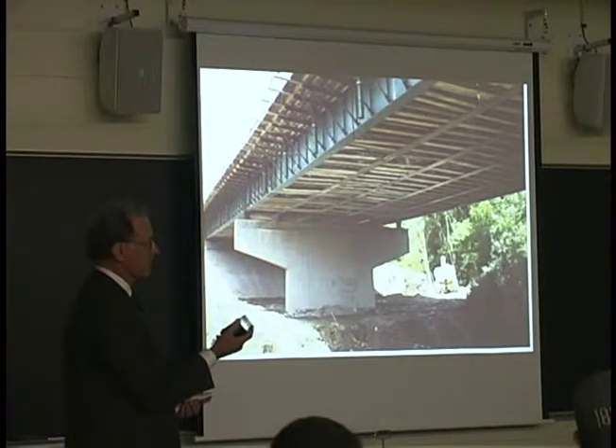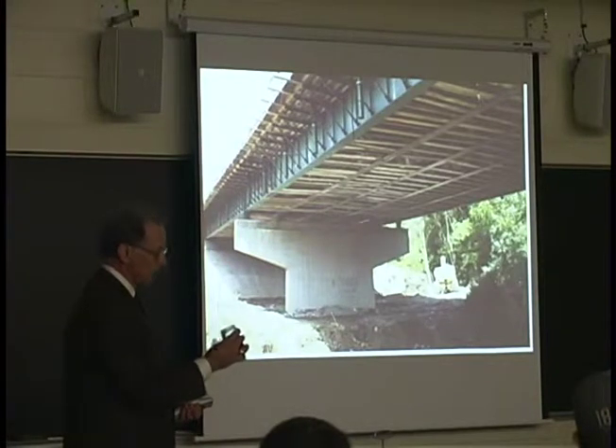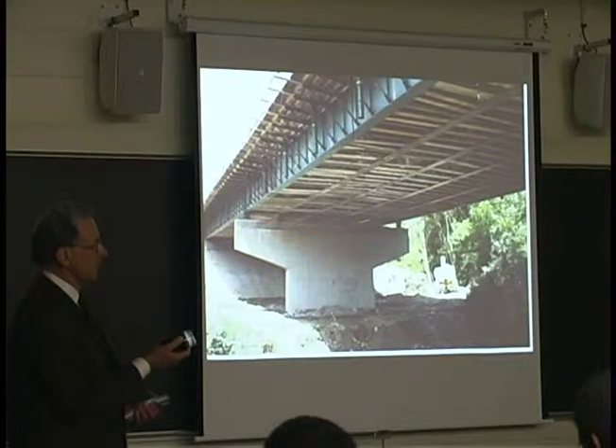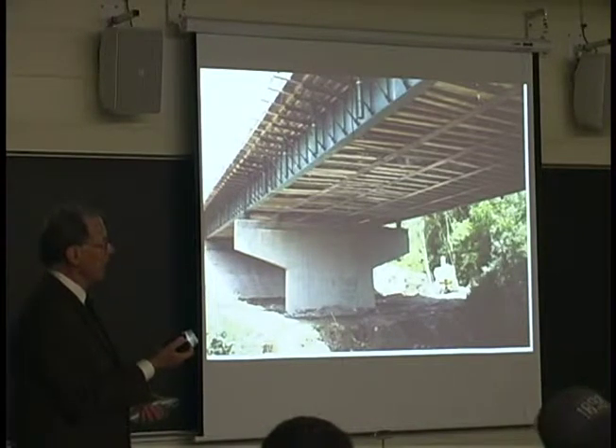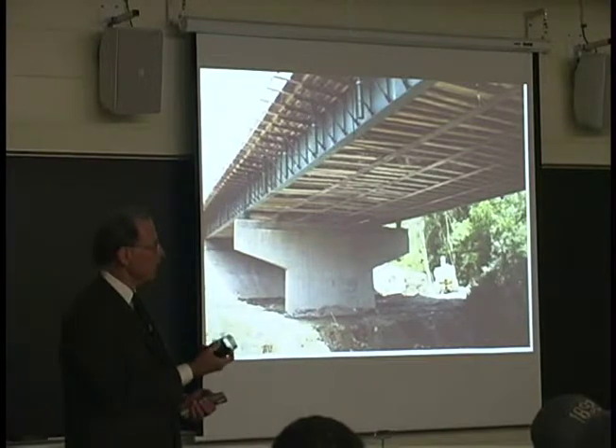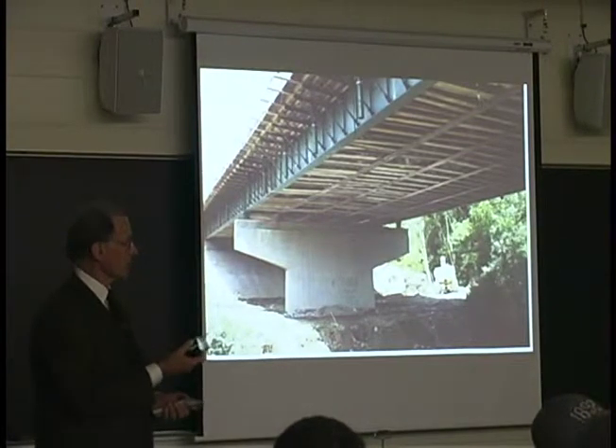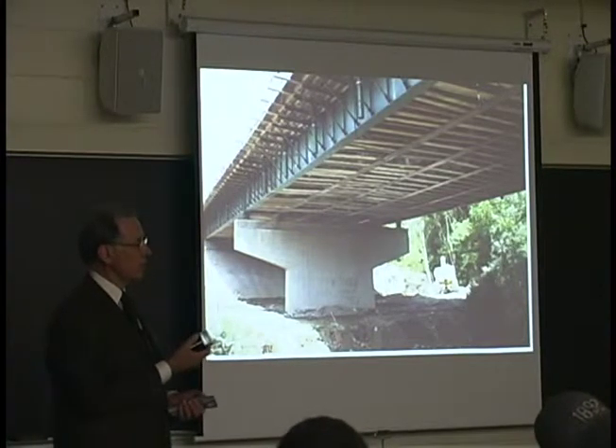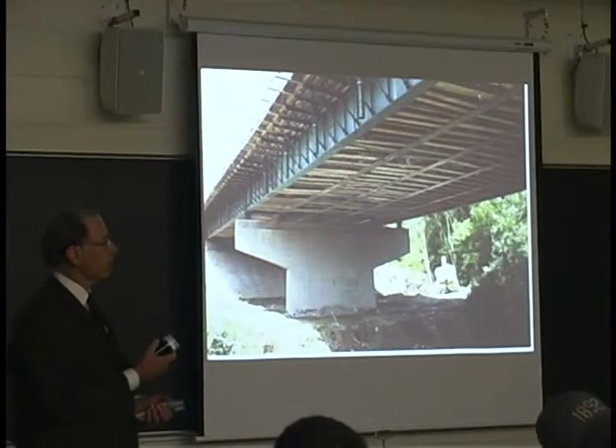Now, what temperature would make it fluid? You're probably going to be required to keep that at about 350 to 400 degrees Fahrenheit in order to get it to flow through your pipes and your spray bars and those types of things. You make the mix, and how long would it take from the plant to drop it where it should be? I'll get into that too, but you have about an hour.